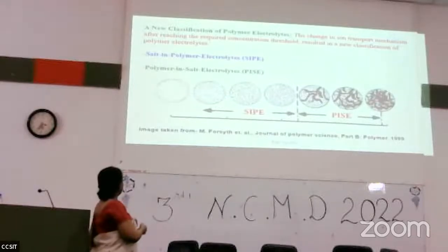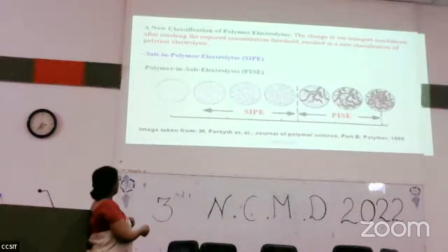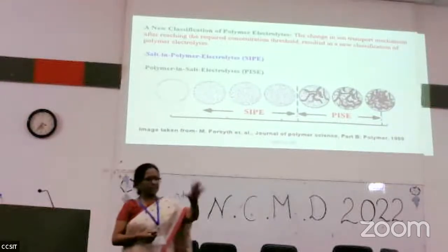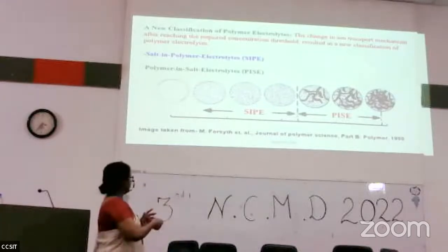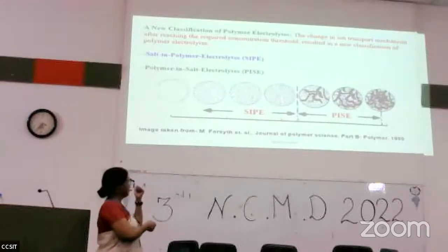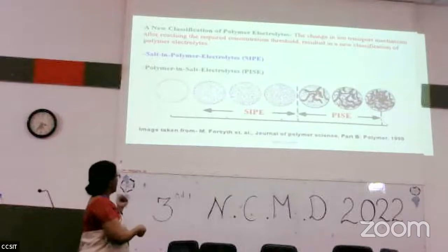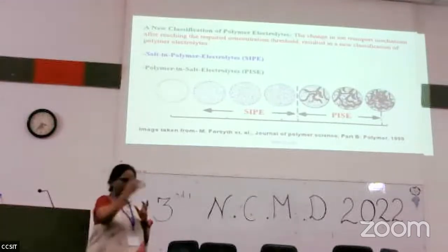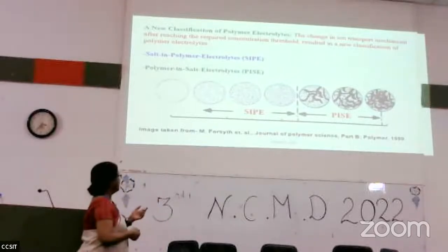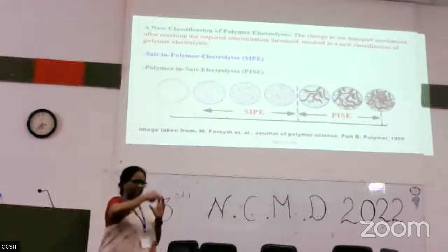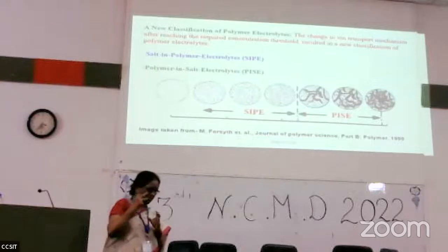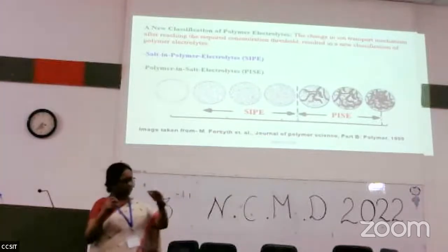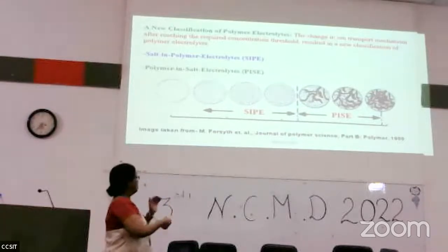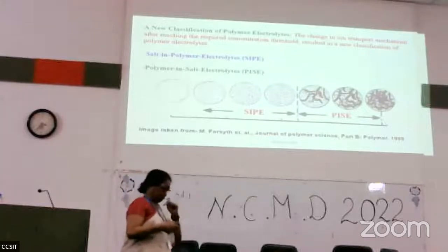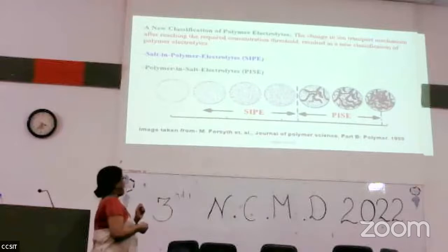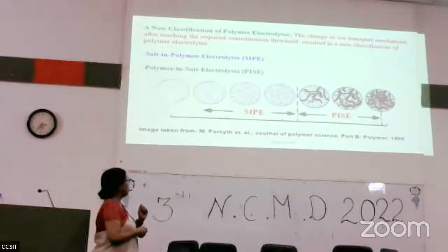So they are distributed. They are not connected. So in this case, they result in a decrease in the conductivity, which is actually the dip point in the previous. Then they start connecting with each other, and when they start connecting with each other, a new very high conductivity is very fast, and also the ion transfer number has been shown like this.